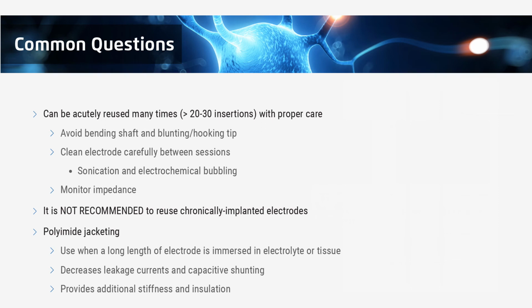Electrochemical bubbling is a very important process that returns the actual electrode surfaces to a mirror finish. How it works is that you apply a constant voltage of -3 volts. It's very important to note the polarity of this. You want to make sure that the negative pole is connected to the electrode, as if the positive pole is connected to the electrode, it can actually drive the metal to corrode and ionize into the solution. A common way to generate this voltage is by using just 2 AA batteries in series. It's an excellent way to do it.